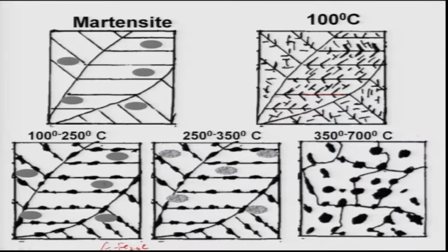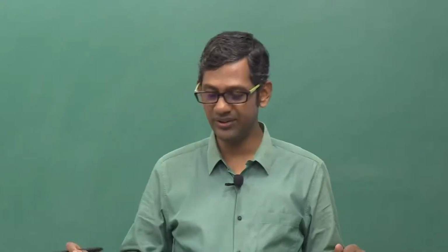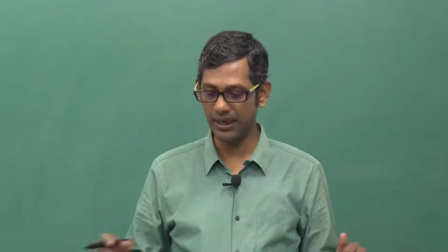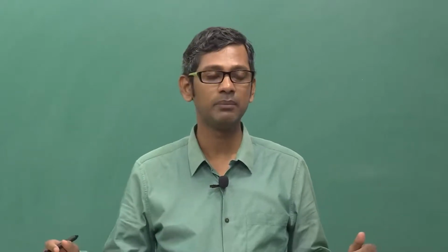And because Fe3C will come out, the remaining grains will become alpha. So complete carbon partitioning happens from the grains of martensite to Fe3C, and slowly Fe2.4C, Fe2.46C will transform to Fe3C. So finally we will have a microstructure with a coarse, near spherical Fe3C along with the alpha grains, the same kind of phases like pearlite or bainite.